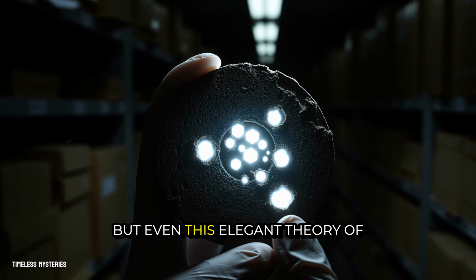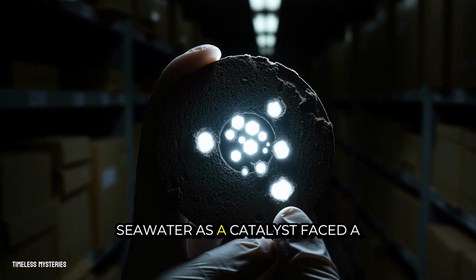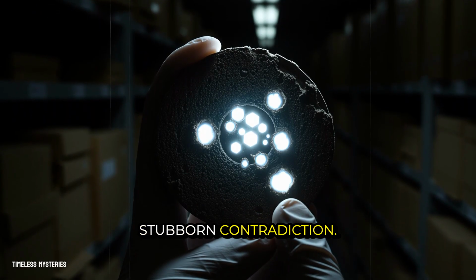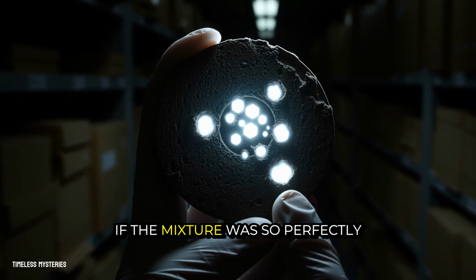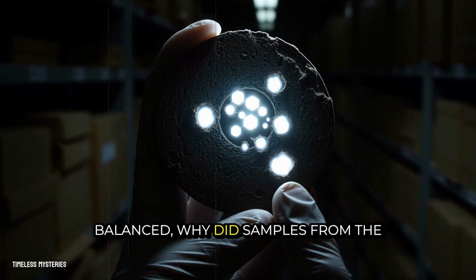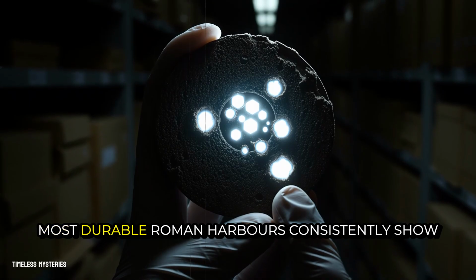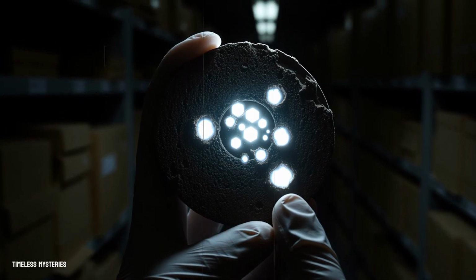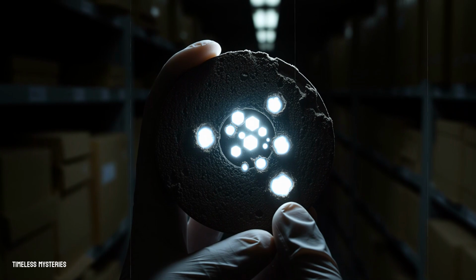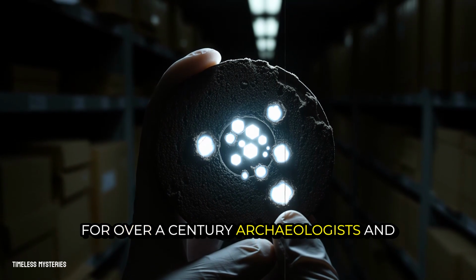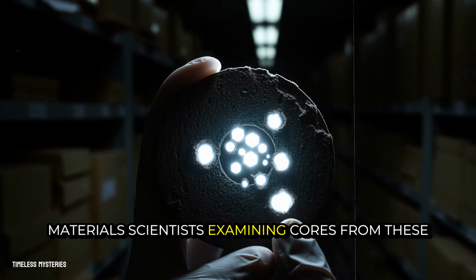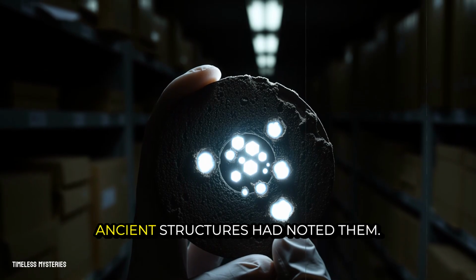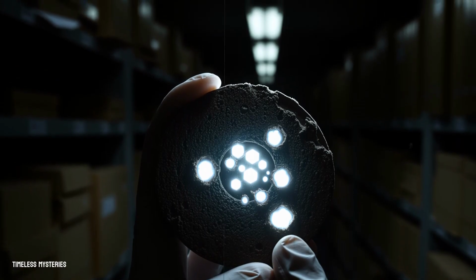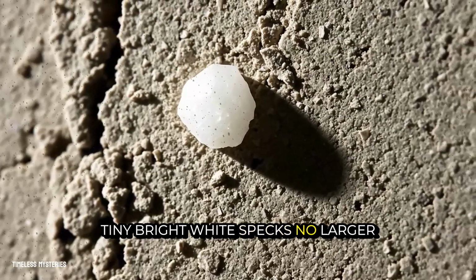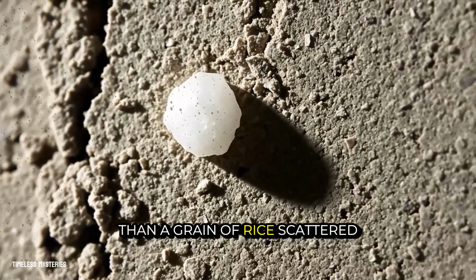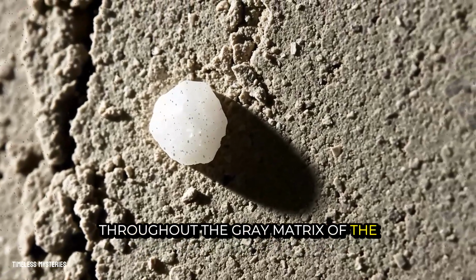But even this elegant theory of seawater as a catalyst faced a stubborn contradiction. If the mixture was so perfectly balanced, why did samples from the most durable Roman harbors consistently show what looked like glaring flaws? For over a century, archaeologists and materials scientists examining cores from these ancient structures had noted them. Tiny, bright white specks no larger than a grain of rice scattered throughout the gray matrix of the mortar.